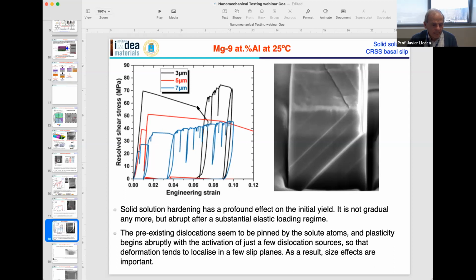So you can see that the pre-existing dislocations in this material, in the 3 by 3 microns micropillar, are pinned by the solute atoms, and then plasticity develops abruptly with the activation of a few dislocation sources. So deformation tends to localize in a few slip planes. As a result, when you alloy the magnesium with aluminum, size effects are much more important, and this is something that you have to take into account.